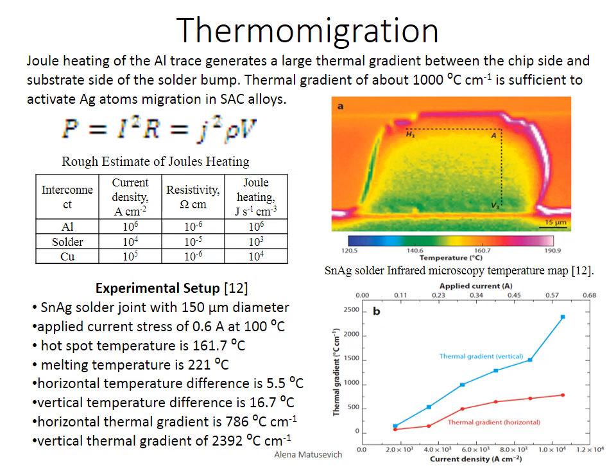As shown in the figure, a hotspot is located at the upper right corner marked by letter A. The temperature of the hotspot is about 162 Celsius, while the horizontal thermal gradient is 786 Celsius per centimeter, and the vertical thermal gradient is 2392 Celsius per centimeter, while a thermal gradient of about 1000 Celsius per centimeter is sufficient to achieve silver atom migration. Thermal migration accelerates the void growth process and accommodates phase separation of silver and tin atoms, leading to the mechanical failure of the flip chip solder joint.